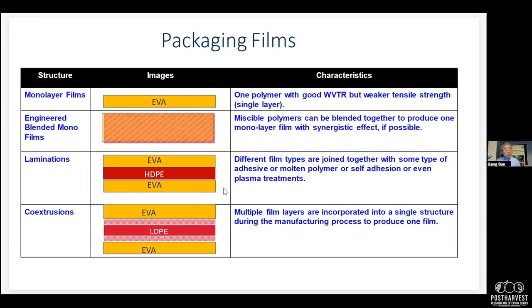The good thing is, as I said, in multi-layer materials a lot of the time they use EVA, because EVA has good adhesive function with polyethylene and polypropylene. Those are the most common and cheaper packaging materials. This is very interesting. There are some other things, but I modified the slides here to show you why these structures vary, and the EVA would be a good one. In fact, I wanted to draw the EVA as a medium layer, and I should make sure that actually the LDPE and the HDPE are the outside layers.